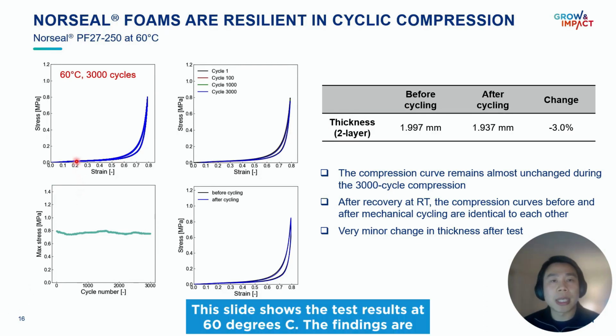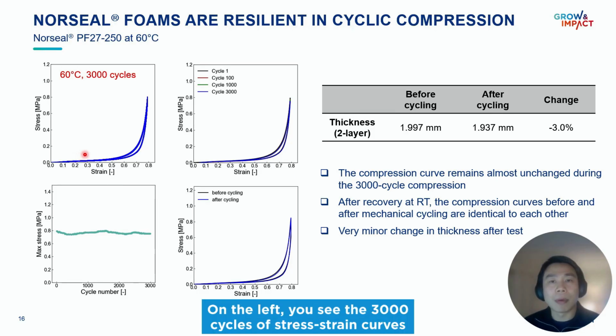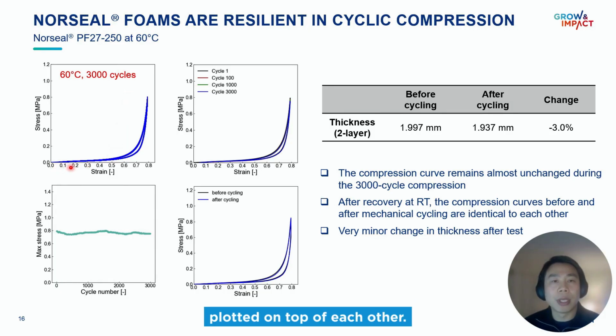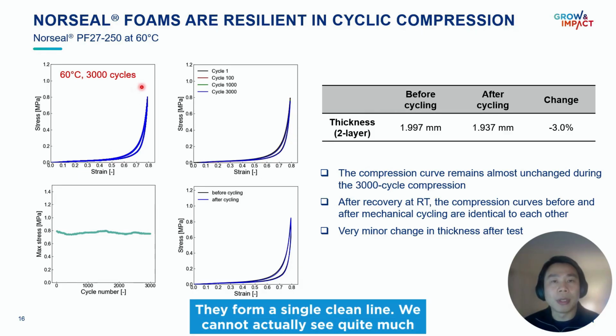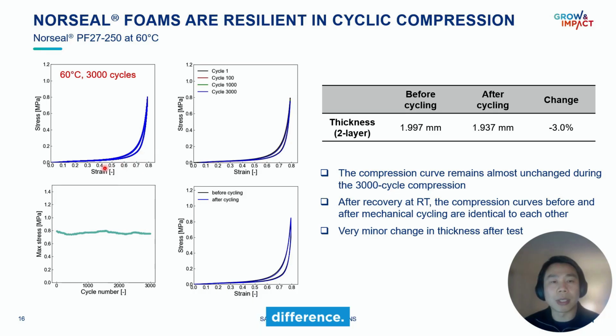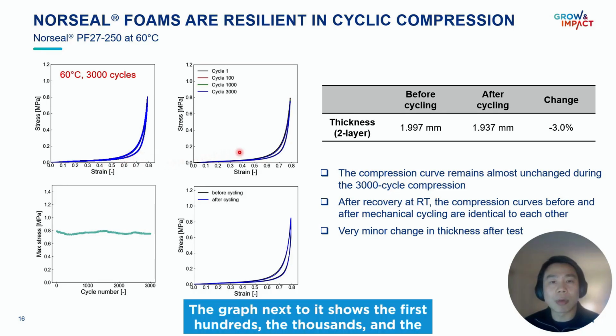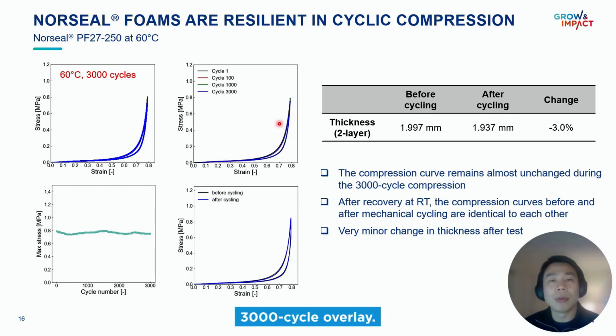This slide shows the testing results at 60 degrees C. The findings are remarkable. On the left, you see the 3,000 cycles of stress strain curves plotted on top of each other. They form a single clean line. We cannot actually see quite much difference. The graph next to it shows the first hundreds, the thousands, and the 3,000 cycle overlay. They are almost virtually identical.